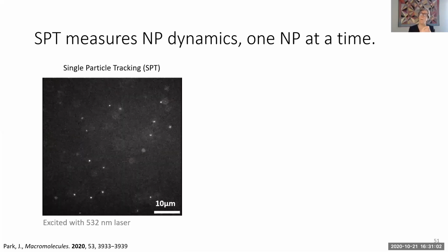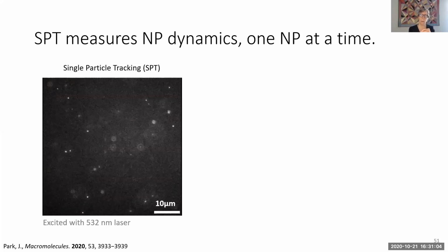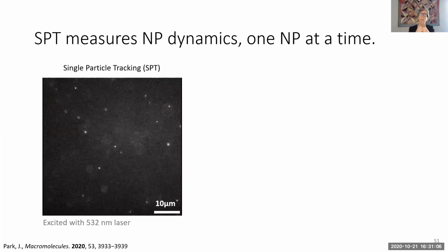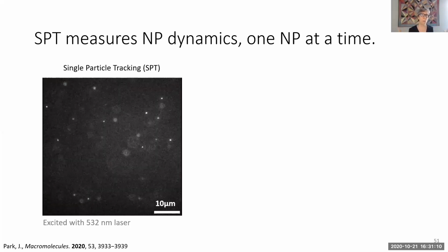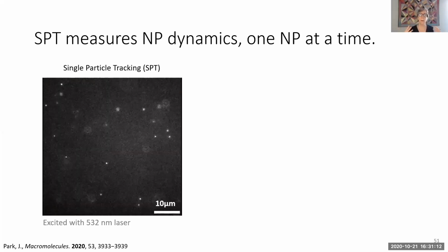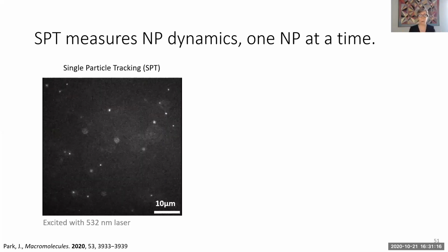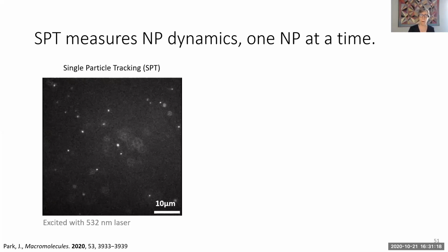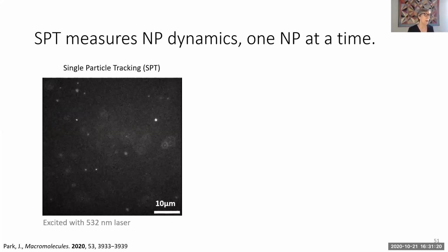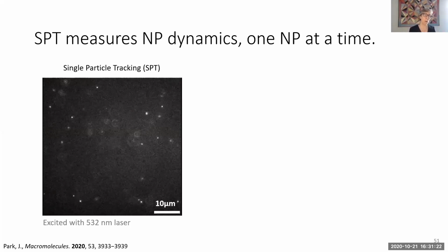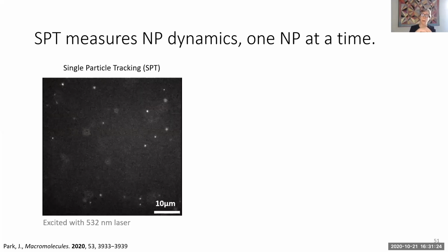But if you have a neutral surface, the particles are going to find each other and get stuck. And these diffusion experiments are long, so we really need to find a way to circumvent particle agglomeration, because we don't want to measure groups of particles moving. That would be even slower. So we went to single particle tracking so that we could look at the effect of the particle-polymer interaction.